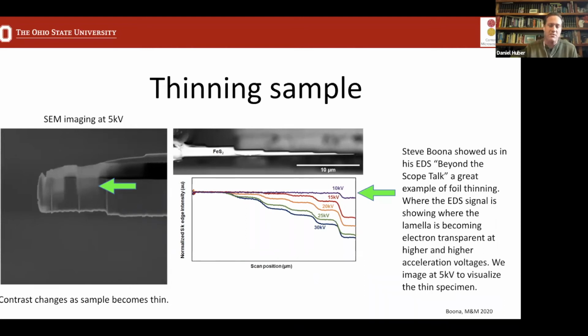So our trick here is we're going to view the sample over here on the left-hand side, in the SEM view at 5 kilovolts. As the electron beam is hitting the specimen and we're thinning with the ion beam simultaneously, as the sample gets thin enough that the beam starts to transmit through the specimen at 5 kilovolts, the contrast mechanism forming the image changes.